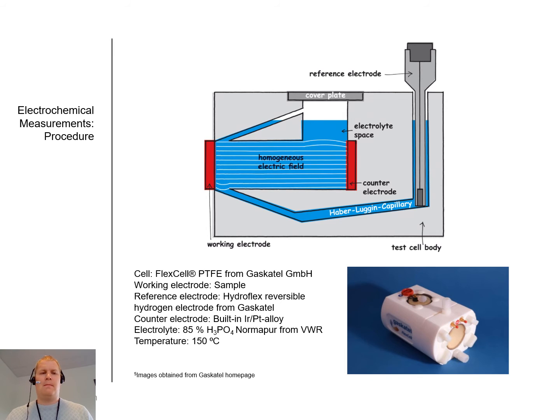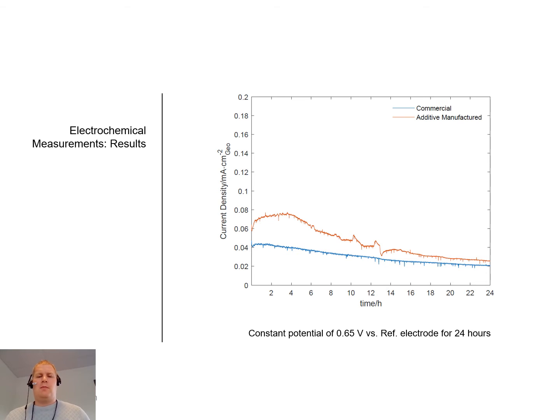150 degrees C. One of the experiments we conducted was so-called chronoamperometry, where we measured the current while holding the sample potential constant at a value of 0.65 volt versus the reference electrode for 24 hours. In the literature, it's reported that the cathode in a high-temperature PEM fuel cell during normal operation experiences this voltage.